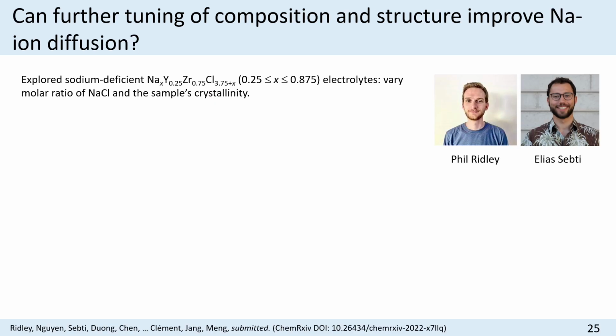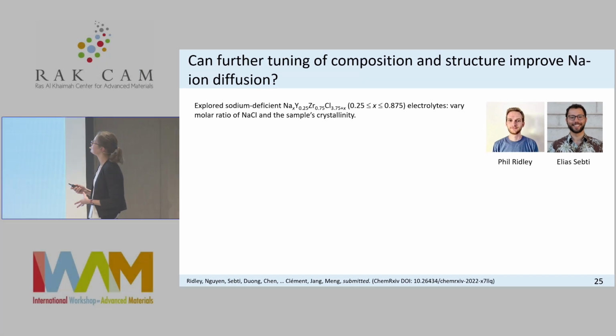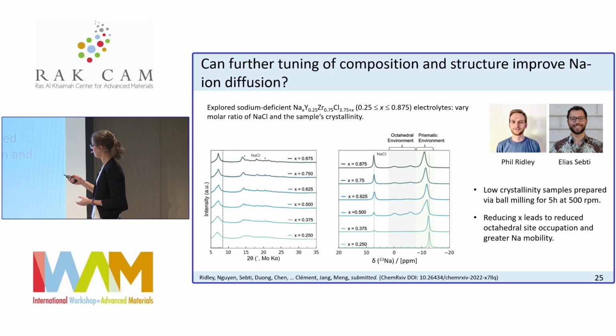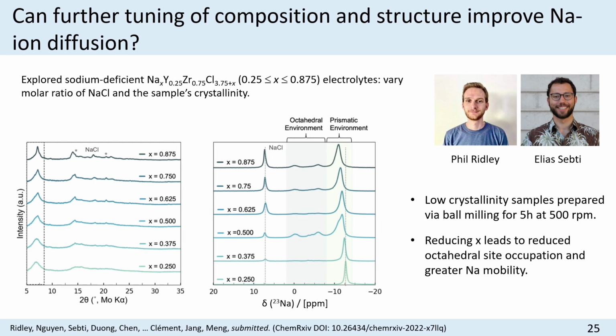So with all of this understanding of the need to create sodium vacancies in these materials and the need to mix transition metals, we decided to further continue tuning this family of compounds to improve ionic conductivity. And the next step was to form sodium-deficient systems, where we now are tuning the molar ratio of sodium chloride that we have initially in our synthesis pot, if you want. And we also tune the sample crystallinity. So all of these materials, this is the sodium content now in your material.